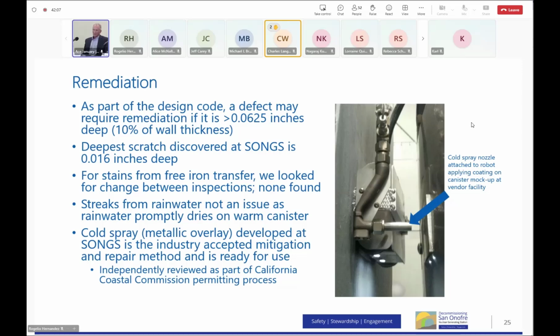So our evaluation of a scratch wouldn't be so much concerned about the depth of the scratch, because the depth of a scratch is never going to approach a technical issue. It's more about what caused the scratch. We're more interested in what would have caused the defect. I say scratch, but there are lots of different defects that could cause it. Our deepest scratch in the Holtec system is 16 thousandths of an inch. There's a slightly deeper one in the TN system, but nothing that's even approaching the 62 thousandths of an inch.